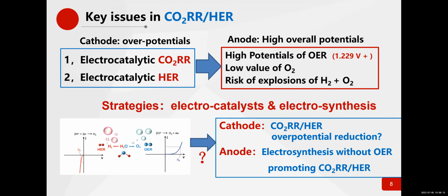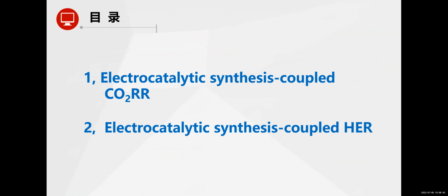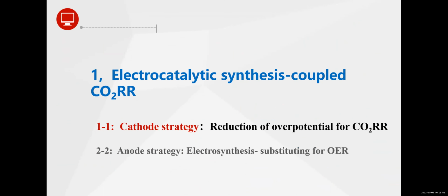So our strategy can be applied to both the cathode and the anode. At the cathode, we try to synthesize suitable catalysts to lower the overpotential of carbon dioxide reduction and HER. Second, we think it is more important to try to realize so-called electrosynthesis to substitute for OER, and also to promote the carbon dioxide reduction or HER. We will first pay some attention to electrocatalytic synthesis coupled with carbon dioxide reduction. But before talking about that, we first pay some attention to the cathode, to try to reduce the overpotential for carbon dioxide reduction by using suitable catalysts.